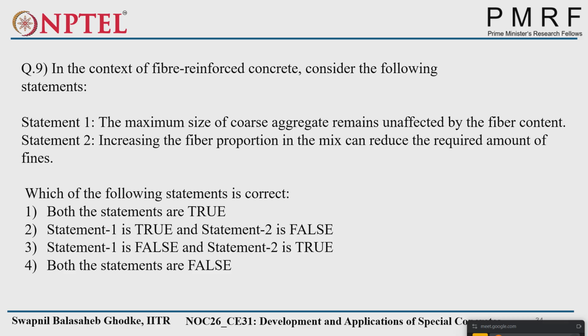Okay, both are false is the correct answer, because the maximum size of coarse aggregate we have to reduce because of the fiber content. We cannot say it is unaffected, because we should not have a more congested concrete matrix. Then increasing the fiber proportion can reduce the required amount of fines? No, we require more fines because of the increased overall specific surface area, and to carry all the fibers and the coarse aggregate along with the concrete matrix in the flow. So both statements are wrong.